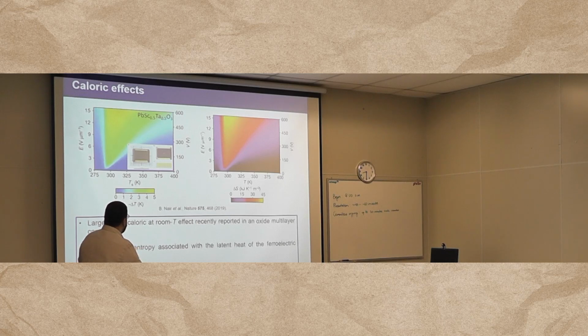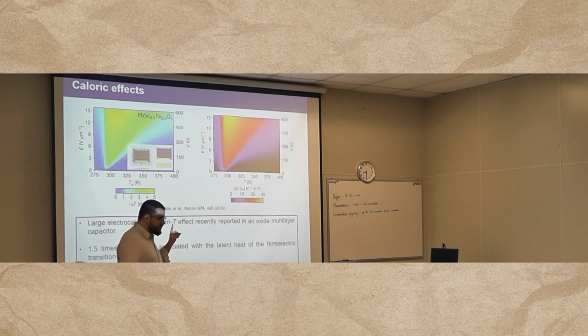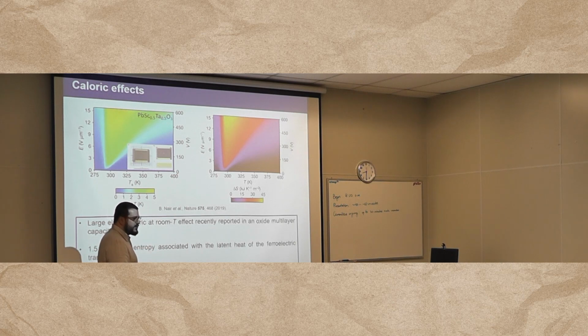This nice paper was published in Nature in 2019. This was associated with a so-called multilayer capacitor of this system, and they had seen a large electrocaloric effect in the system with a variation of temperature of about 5 Kelvin. So they have seen that close to this region where the entropy varies greatly, the adiabatic variation of temperature is greater. And this is very interesting because this electrocaloric effect is performed close to room temperature. And this is very crucial for technological applications.